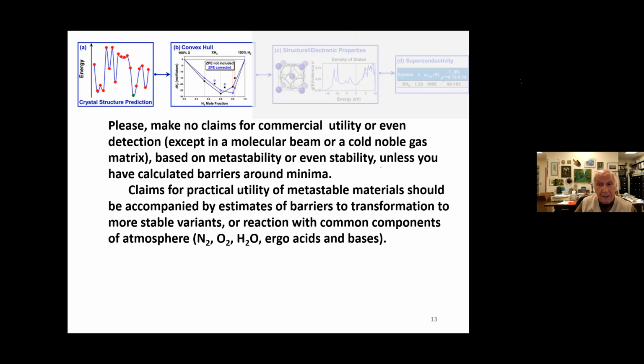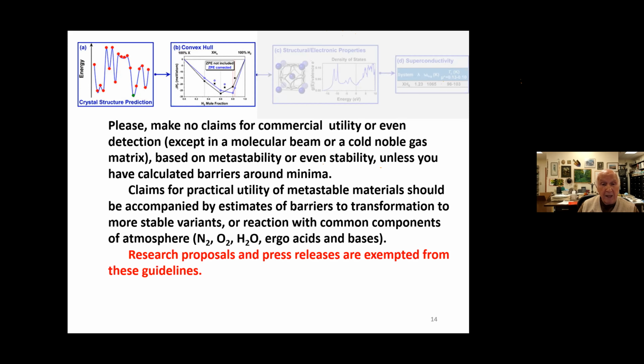I've just shown you stable molecules that are very reactive unless you have calculated the barriers around those minima. Claims for practical utility of metastable materials should be accompanied by barriers to transformation to some more stable variant of what it is. Also, if you really want to sell the stuff on Earth that you're making and you're claiming the cat's pajamas for the properties of some given material, you better calculate the barrier for its reaction with various components of the atmosphere, which are N2, O2, and the worst actor in the atmosphere is the little humidity we have. That is because water is both an acid and a base and very reactive. Research proposals and press releases are exempted from these guidelines.